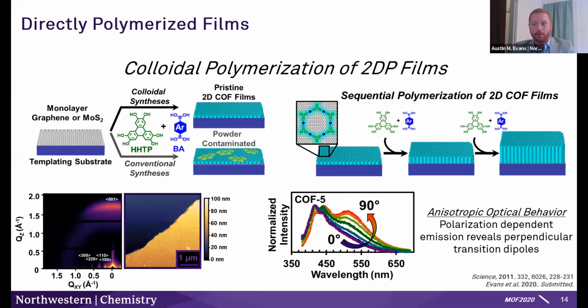And I don't know if you'll remember, but back to my earliest slide, folks have speculated that anisotropic optical behavior should arise as a function of the perpendicular transition dipoles in these different materials. And indeed, we can observe that using polarized fluorescence. And I think this is a really neat measurement because it corroborates the highly oriented nature we observe by